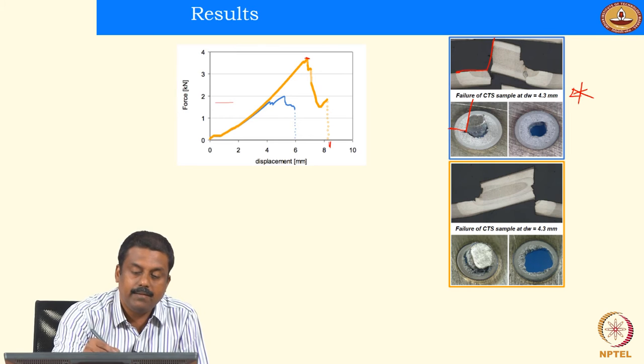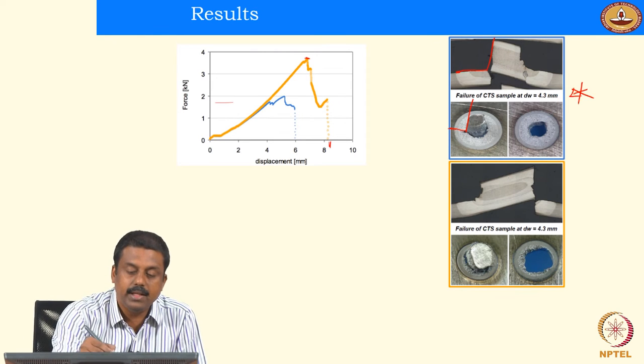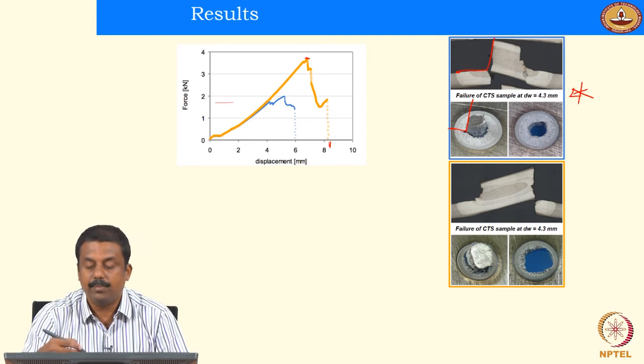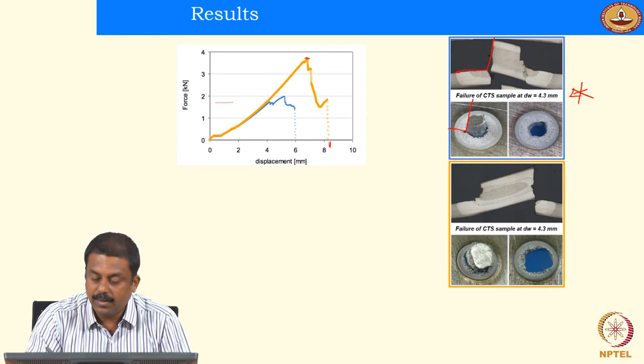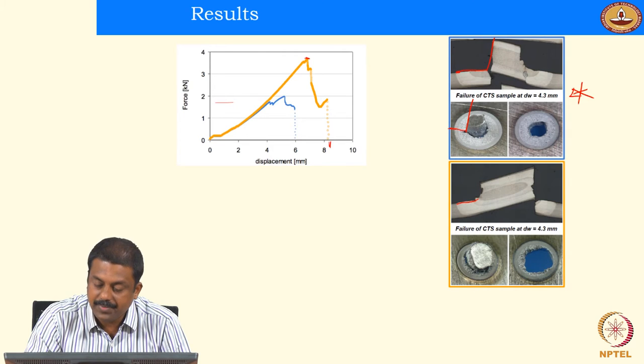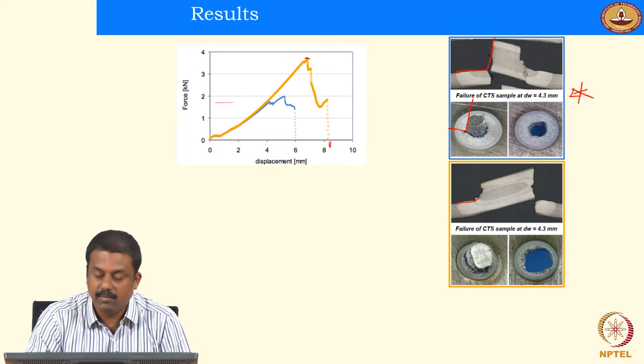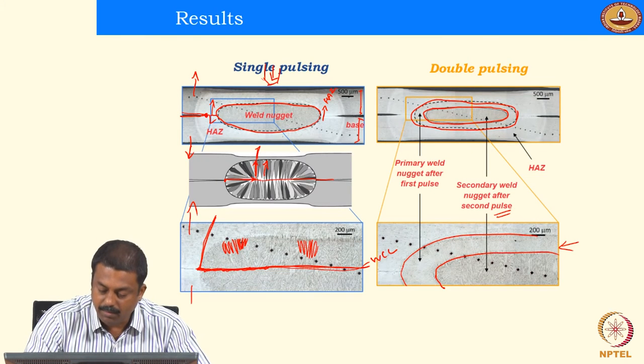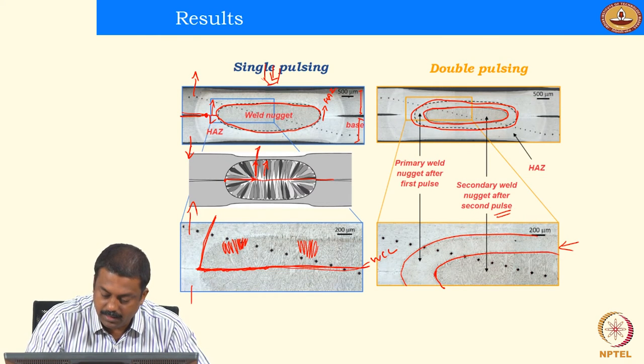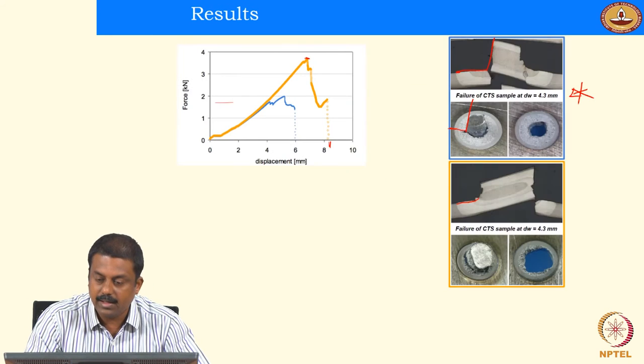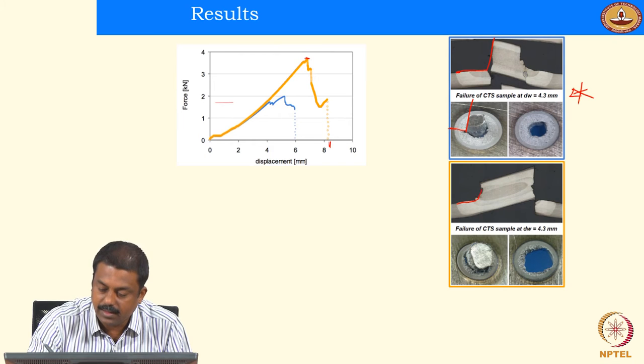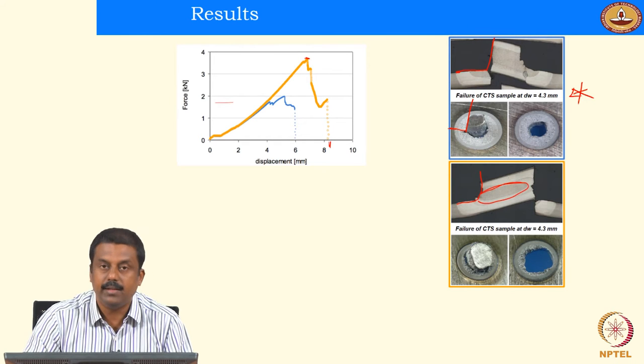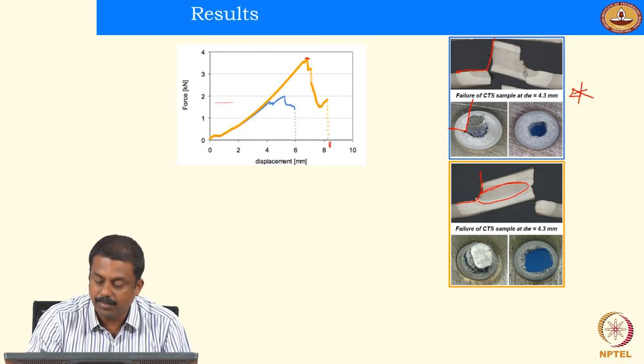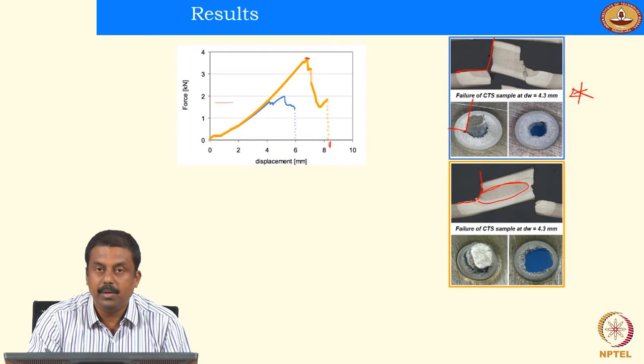And in the second case, when you have a double pulsing, you see the strength is increased and displacement also increased, that means the mechanical properties are improved significantly. So if you look at the failure mode, the moment the failure is initiated, and then reaches the region where you see a boundary between the primary and the secondary weld nugget, the crack is deflected. That means that your weld nugget is intact, the majority of the secondary weld nugget is intact. So you improve the mechanical properties significantly by doing a second pulsing.